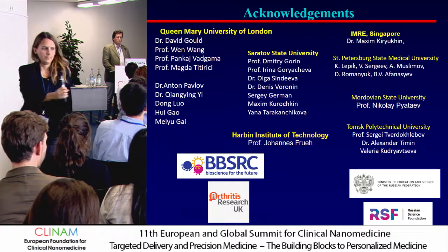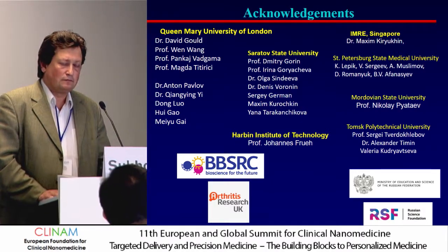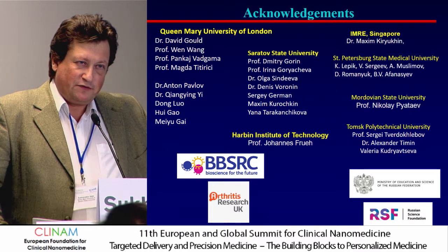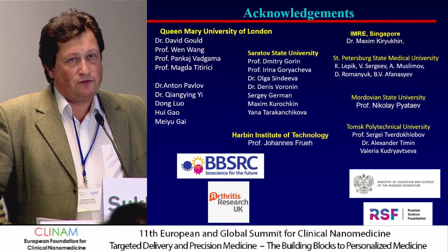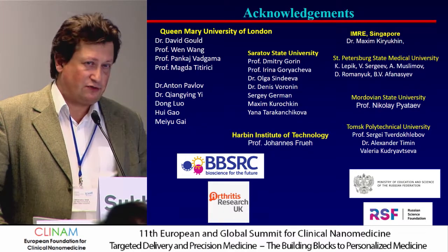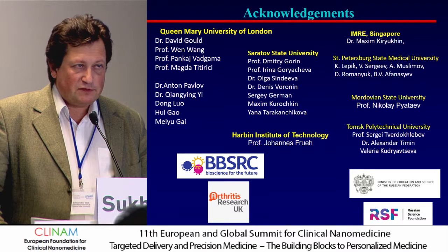So thank you. Maybe I missed this, but what's the size of these capsules you used to integrate into cells? Well, the capsules start from 50 nanometers and go up, there is no upper limit. And what I showed to you was a few microns. The cells could take the capsules up to 4 microns inside. The smaller they are, the more difficult to work with, with ultrasound, yeah.